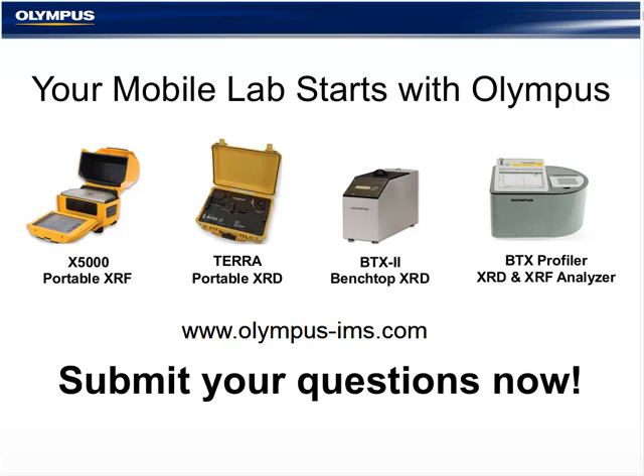So this is really a two-part question. I'll take the first part in regards to sample requirements or instrument requirements. For the instrument, we supply a manual crusher with our instruments along with a 120 mesh sieve. Simply grind, sieve, load a small amount of powdered sample into the sample cell.